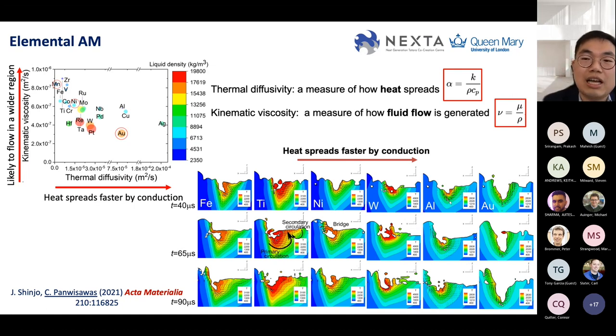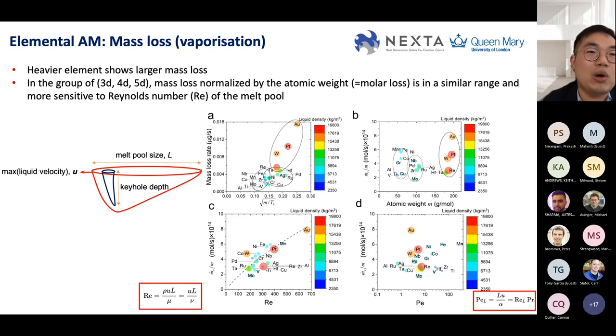I mean, all this has been summarized into a diagram we call the elemental AM diagram to understand the characteristic, especially the vaporization or mass loss. So it seems that the heavier elements show larger mass loss in the group 3D, 4D, 5D. The mass loss normalized by the atomic weight is similar in range but sensitive to the Reynolds number of the melt pool. The Reynolds number, as you know, is defined here on the left-hand side: the maximum liquid velocity and the melt pool length scale, which is given as a characteristic length for the Reynolds number calculation here.